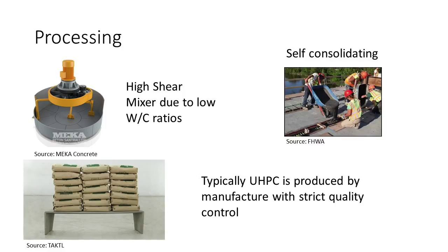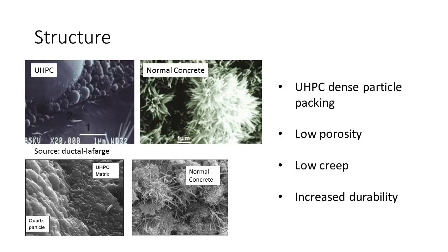Because of the low water-to-cement ratios, it needs high range water reducing admixtures to help control that water-to-cement ratio. Because of that, it also becomes a self-consolidating concrete, which doesn't need to be vibrated to be placed in and around reinforcing steel. That also helps it with some of the other properties that I'm going to get into.